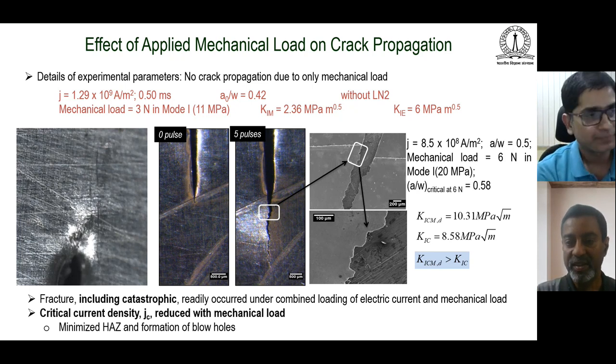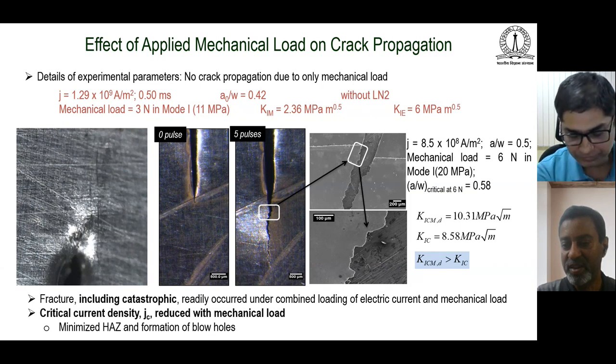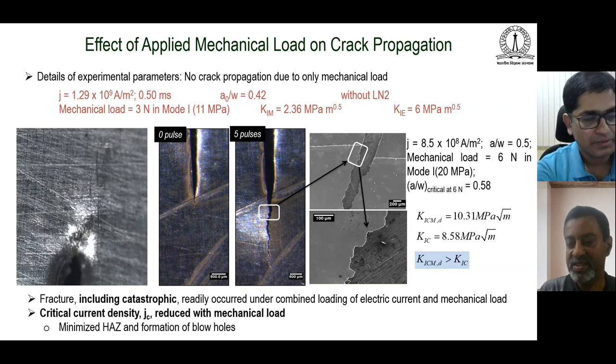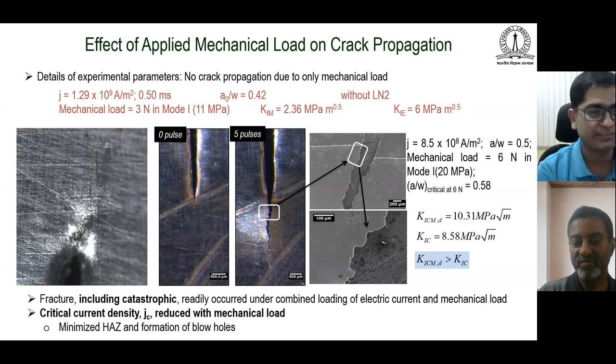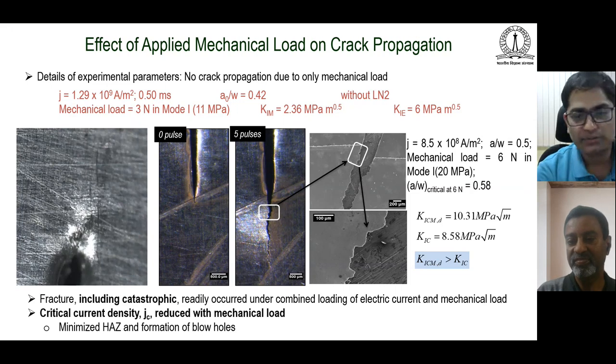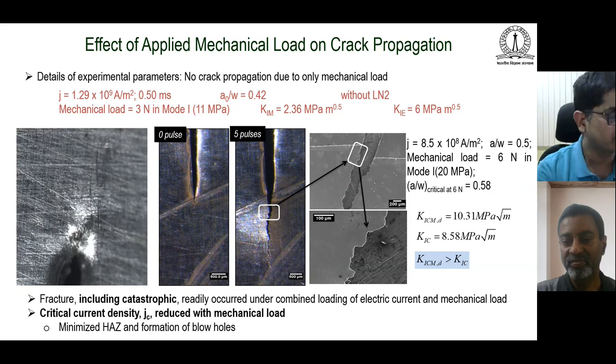Then there is also a follow-up question regarding the direction of crack propagation. Doesn't the crack propagation direction depend on the grain structure of the material, aside from the external factors which you can control? From the mechanical point of view, cracks will generally propagate along the grain boundaries. That is what he says. All our discussion has been in the continuum realm. The cracks that we are looking at are fairly long, so they themselves have such a driving force that they can overcome the issues associated with metallurgical conditions, like grain boundaries. I'm sure they are playing some role, but most probably not a dominant one.